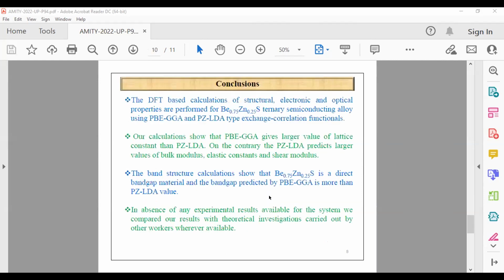So in this work, density functional theory based calculations of structural, electronic and elastic properties are performed for this system, in which we modeled Be0.75Zn0.25S as a ternary semiconducting alloy composed of a 3/4 fraction of beryllium sulfide and 1/4 fraction of zinc sulfide. Our studies show that PBE-GGA gives a larger value of lattice constant than LDA calculation, and consequently LDA predicts larger values of bulk modulus, elastic constants, and shear modulus than GGA calculation.